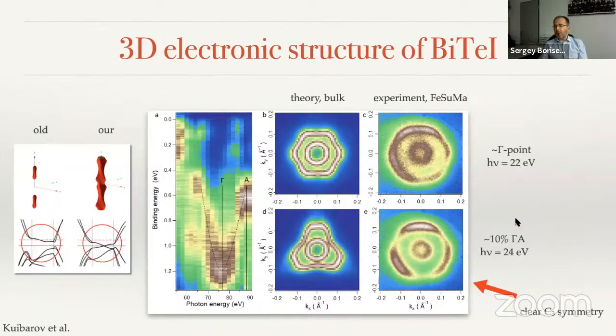But as soon as we go away, approximately 10% towards the R point, A point, we see that the Fermi surface is no longer hexagonal, it's trigonal. And it's just exactly as the calculations of the bulk Fermi surface imply, that you need to have the trigonal, and you see where symmetry comes from. So this is the very typical bulk Fermi surface of this material, and it's very difficult to explain it from the point of view of a purely surface state.